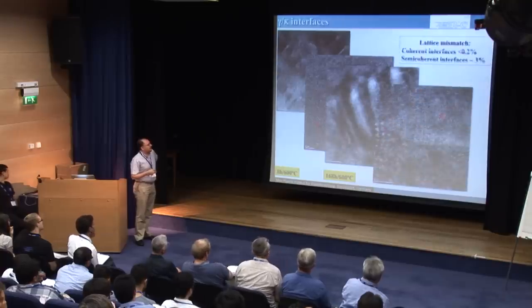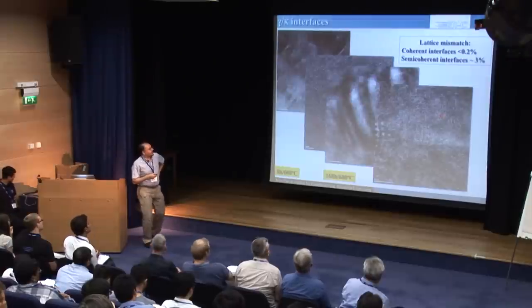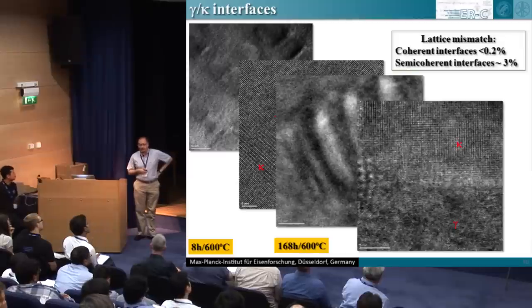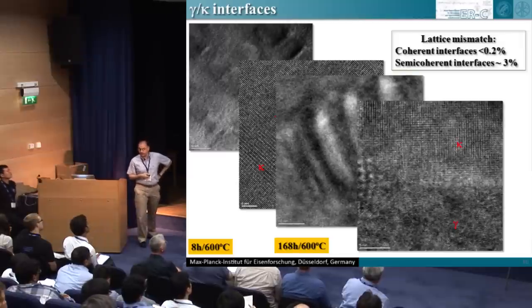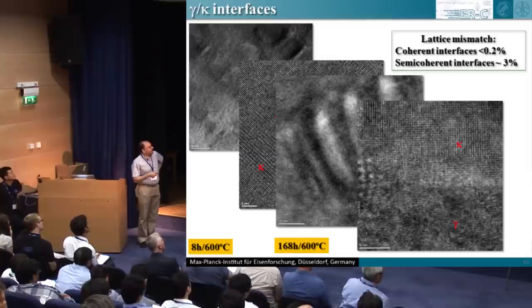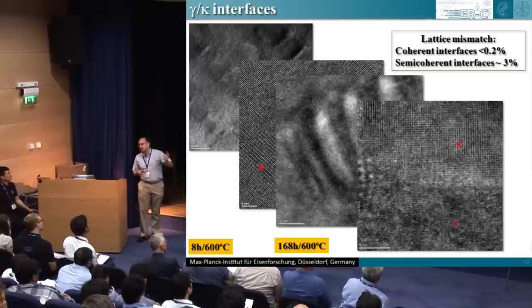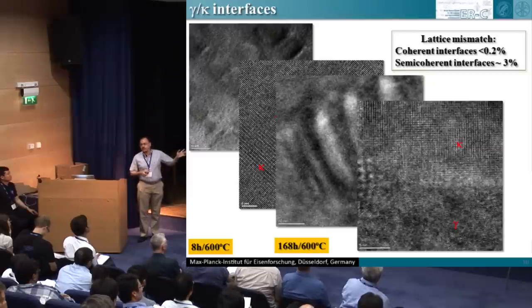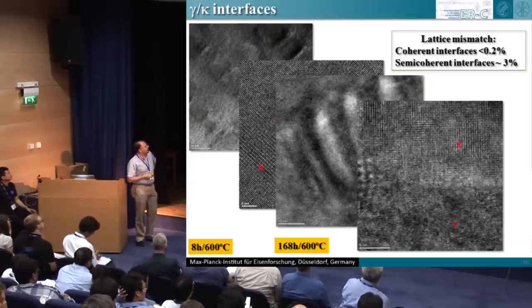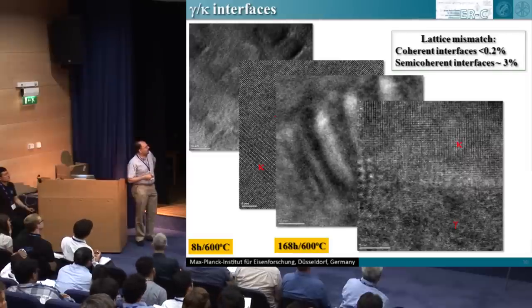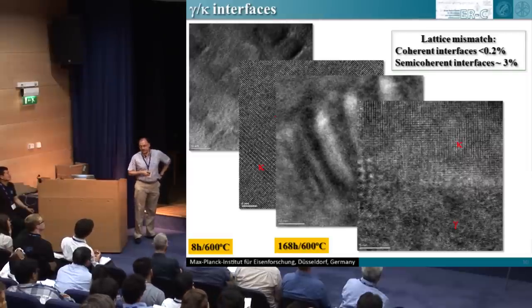So far, these are our estimations, and we have to improve, because we have to deal with extremely thin samples in order to nicely characterize the interface. Our estimates right now look like this, where the coherent interfaces at these annealing conditions are below 0.2%. But we also have semi-coherent interfaces of about 2-3%. According to classical textbooks of materials science, they are more or less coherent, semi-coherent. So this is ongoing, but just to show you the interest in high-resolution analysis of the interfaces of these particles.